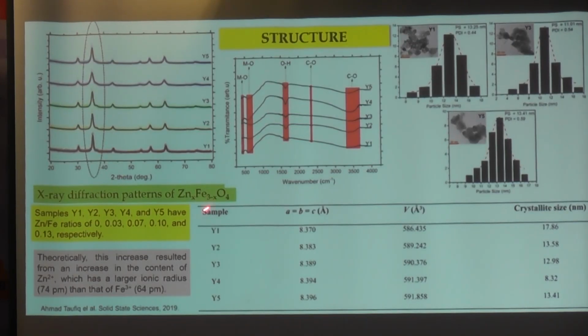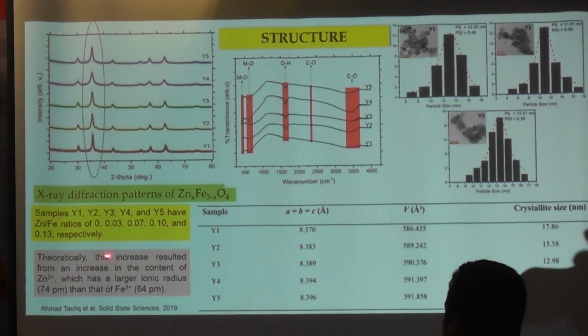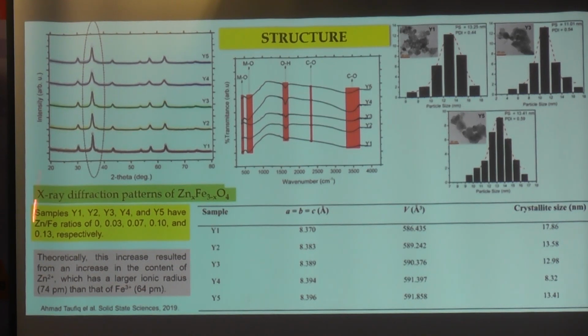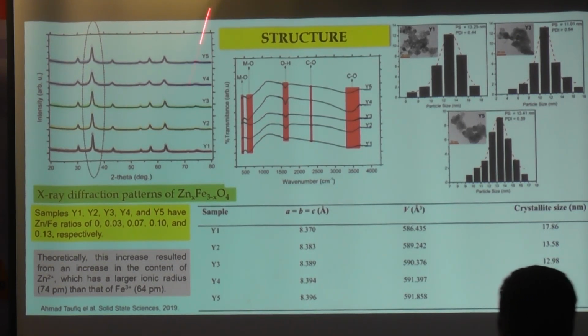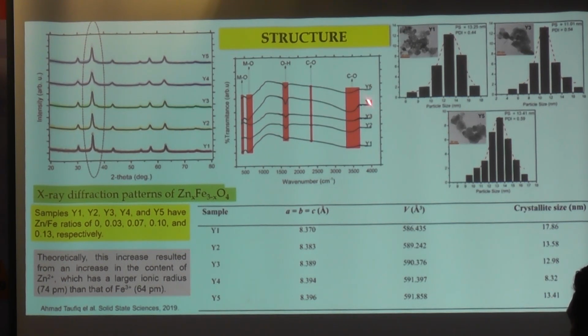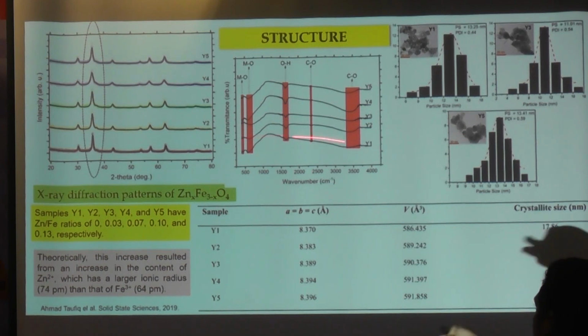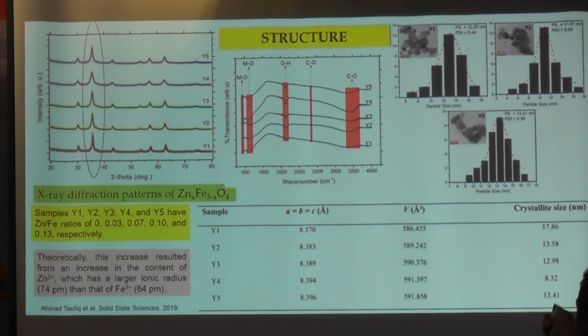Okay. The next is, what about we change the Fe2+ and Fe3+ with zinc? After Mn, we make modification with zinc. We know in here, the lower the theta, the higher the composition of zinc. Zinc also has ionic radii larger than Fe3+. So the peak position moves to the left, or to a lower angle of theta. Based on FTIR characterization, zinc and manganese metal oxide were detected at the lower wave number. And we also combine, this is for powder, using TEM.